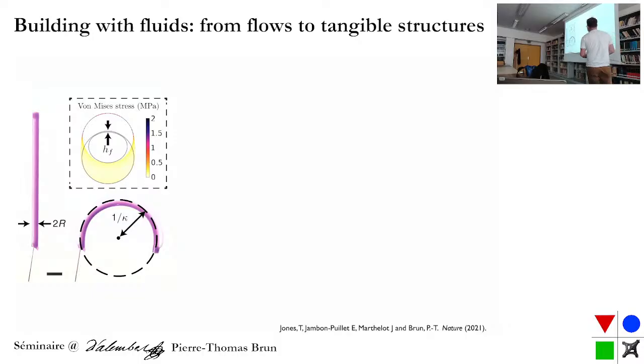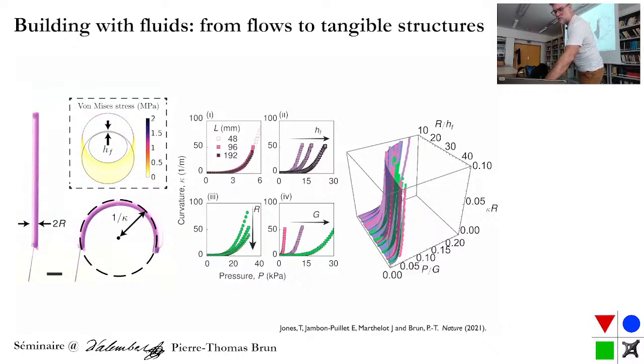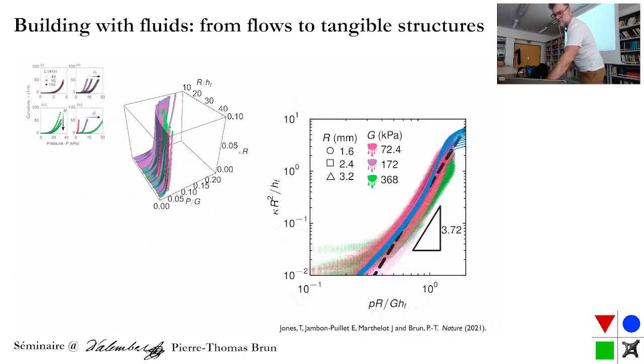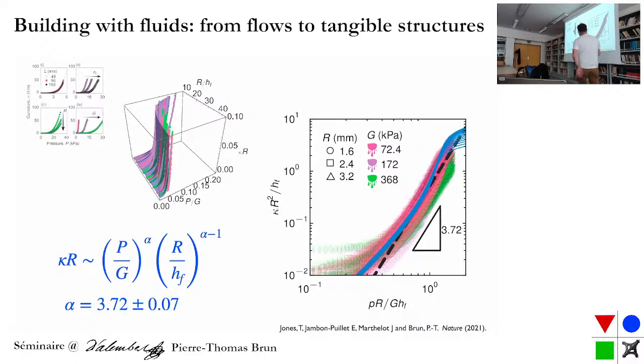Then you can look at the elasticity. I'll go a little bit faster in the interest of time, but as I said, this part deforms more than the bottom, so you're storing excess length in the form of curvature. I really go fast, sorry, but you can convince yourself that the curvature of your actuator will basically depend on the applied pressure, the shear modulus, the geometry, and this HF here that comes from fluid dynamics. So you have a link between the fluid dynamics of the problem and the elasticity of the problem.